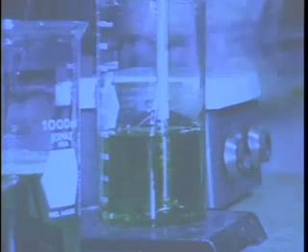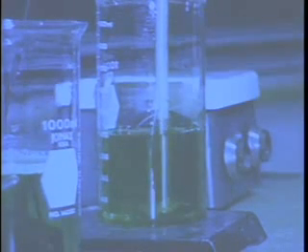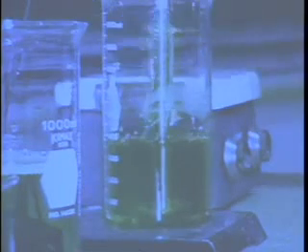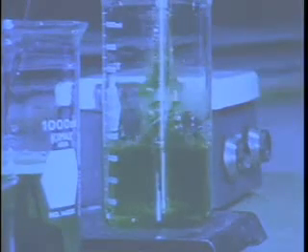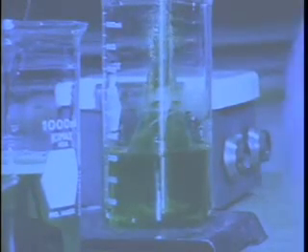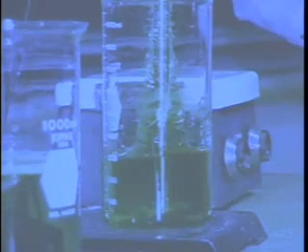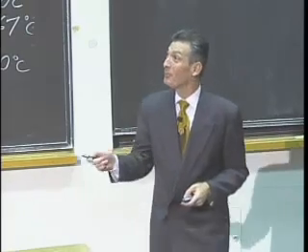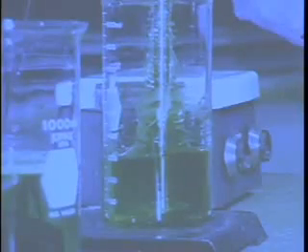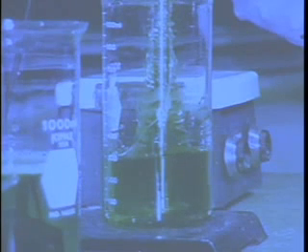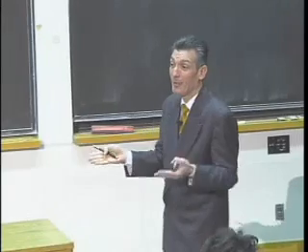Now, when I turn this on, something else happens entirely. It climbs up the stirring rod, and the winging off you see is where I've overcome the centrifugal force and it's being flung out. So there's the Weissenberg effect, and this is at very, very high shear rates. The one thing I wish she'd done is turn the speed down. At very, very low speeds, you'd actually see the vortex form because you're asking the molecules to shear over one another at a slow enough rate that they can keep pace.